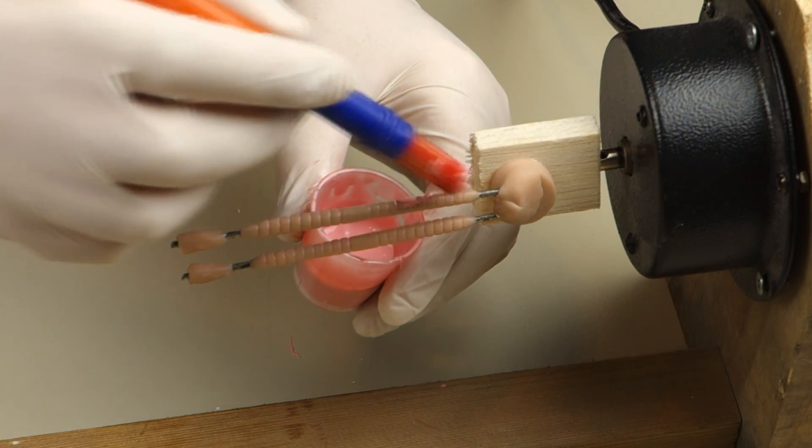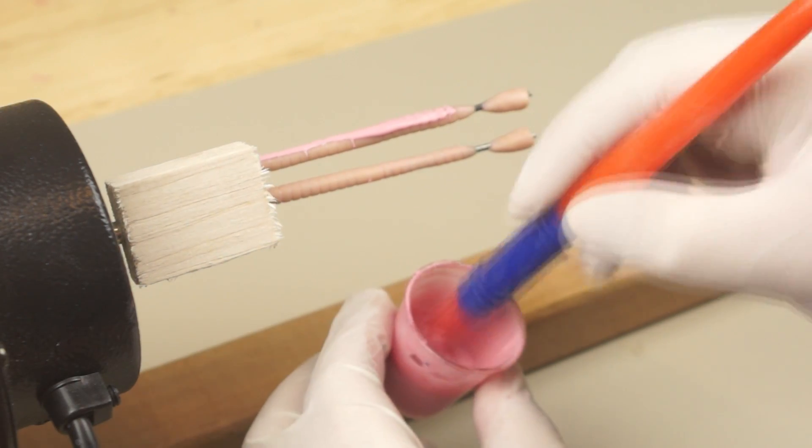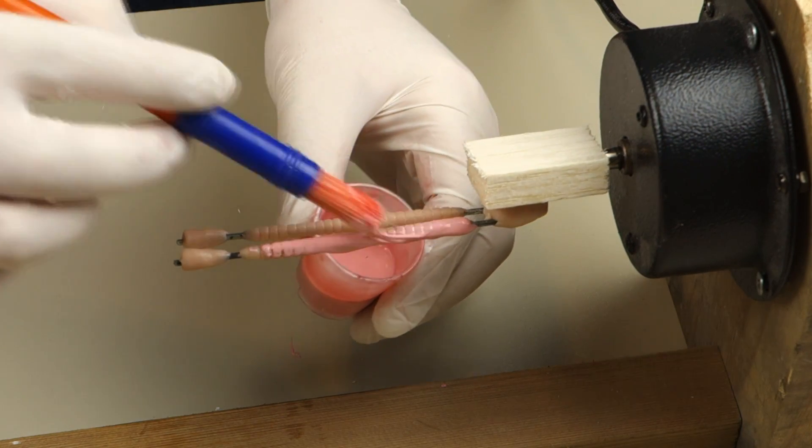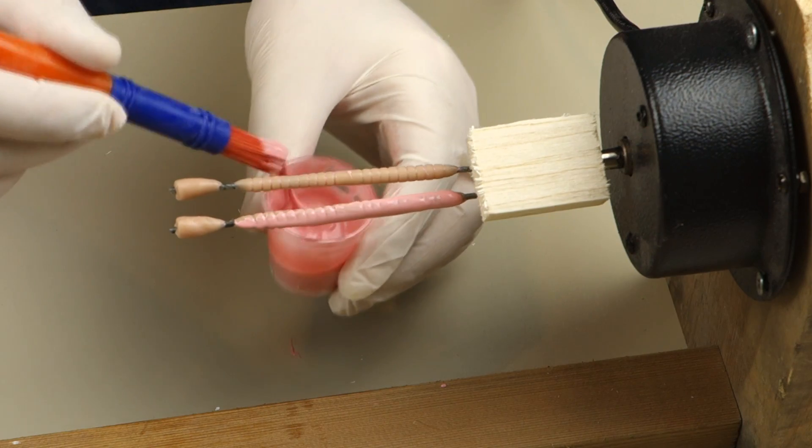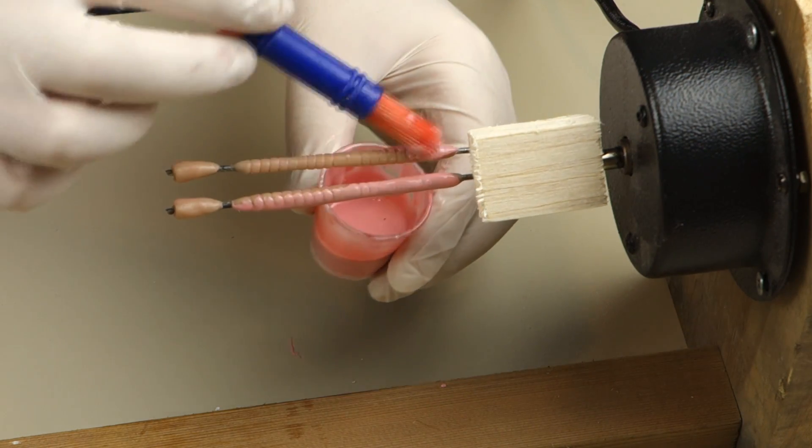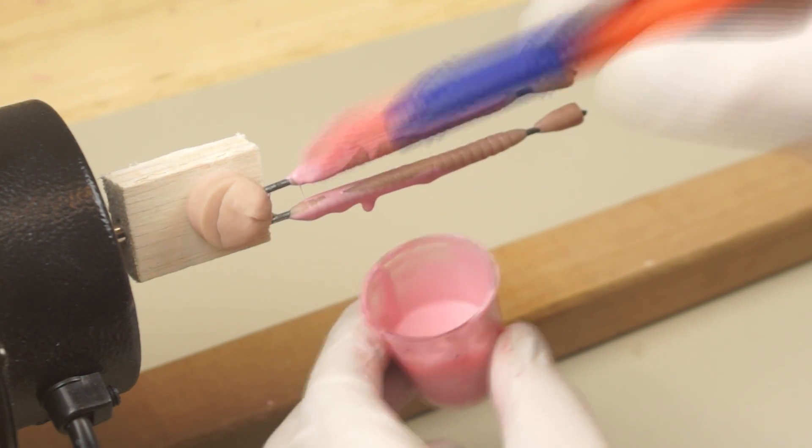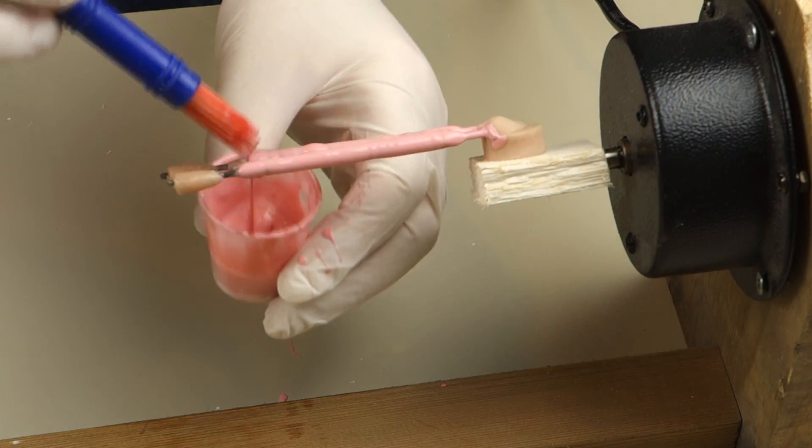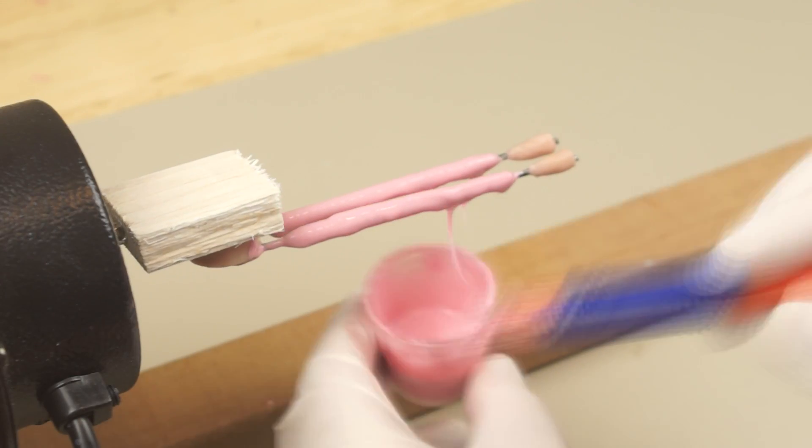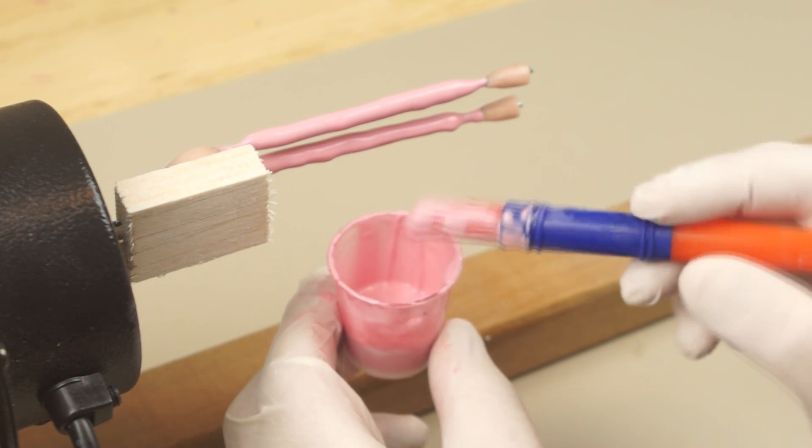To apply the silicone, I'm simply going to brush it and drip it on. It's the same kind of technique as coating with epoxy. And what the spinning should do is allow me to build up quite a thick coat. But also, it should stretch the silicone and pop any bubbles. So I only really need to cover this worm section here in the middle. And once I'm happy I've got enough on, it's really quite overcoated. I can leave that rotating for a couple of hours to settle.